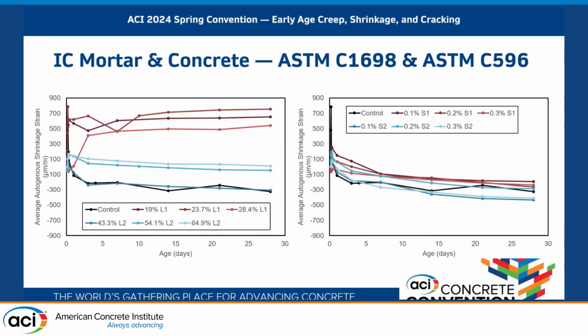This is the same concept, but for after the first day, or at least long term. It incorporates the results not only from the time 0, but up to 28 days of drying. And the performance is characterized for each material based on not only the dosage that it had, but also the absorption capacities or desorption capacities that these materials have.